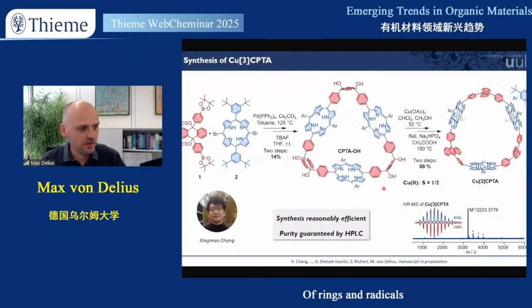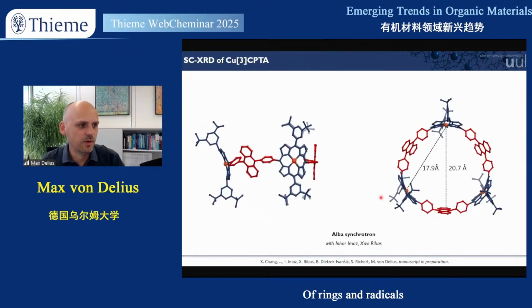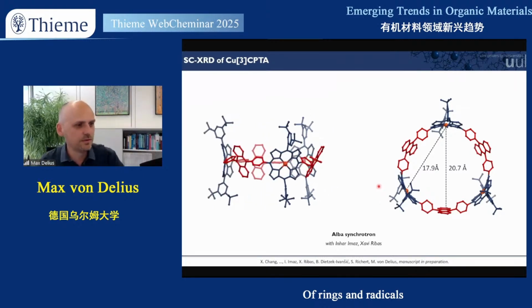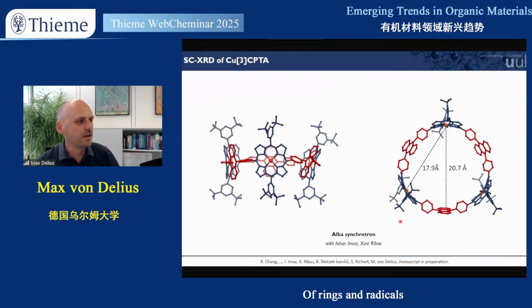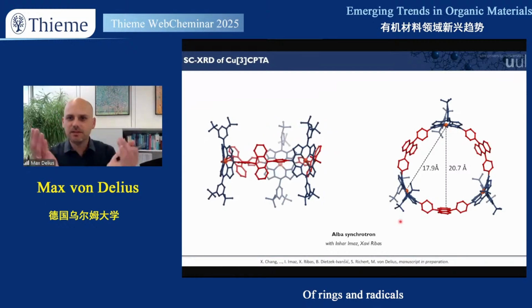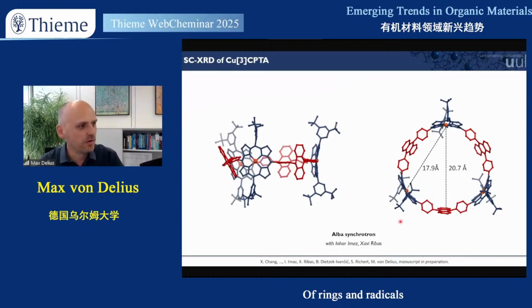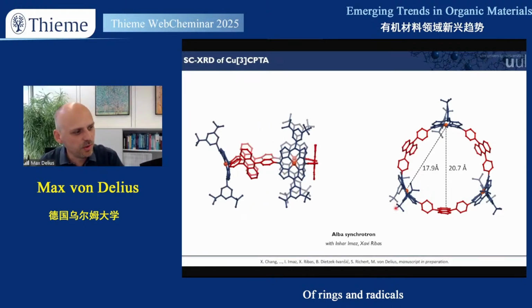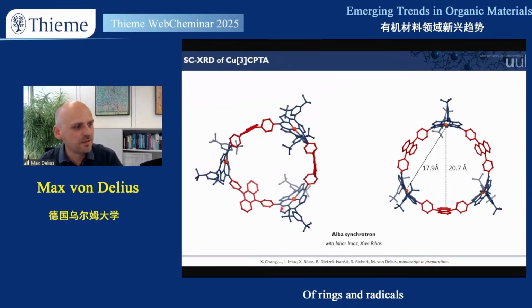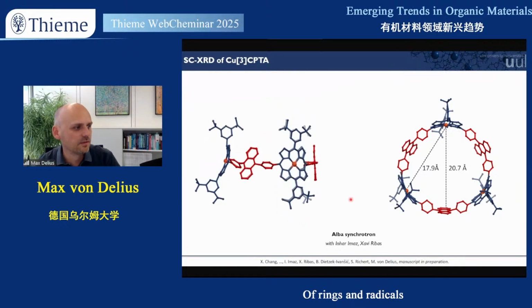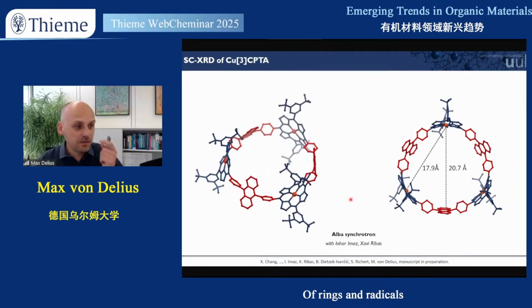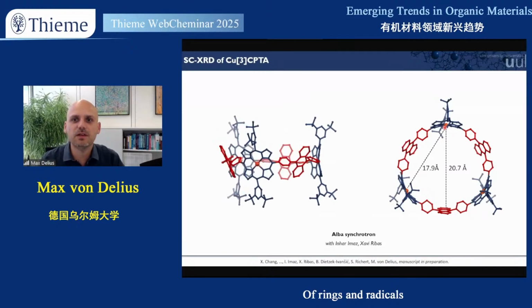So Xing Mao did some great work with preparative HPLC, and we always check via several techniques that our compounds are pure. Xing Mao had good hands, so he grew single crystals, which in synchrotron radiation, we got this beautiful X-ray structure. So you see it's really a nicely circular shape, 3 porphyrins bent together. You see already for a copper porphyrin, this is actually already quite bent. So we see signs of strain in this X-ray structure.